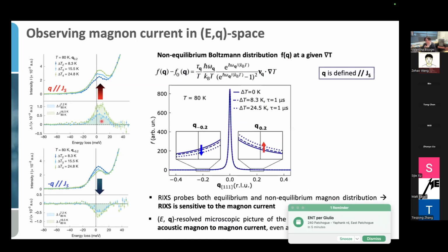And indeed, for a visual comparison, let's now compute the non-equilibrium Magnon distribution function using the YIG related parameters here. And for the momentum related to our study, that is this Q at 0.2 in the reciprocal lattice unit along the 111 direction, we see that as we increase the temperature gradient, the Magnon distribution function is increasing when Q is positive, meaning parallel to the Magnon current, while when we consider negative Q, then the Magnon distribution function is effectively decreasing as we increase the thermal gradient when Q is anti-parallel to the Magnon current. This behavior is exactly what has been observed in our data.